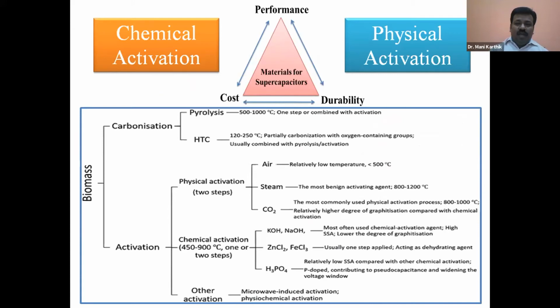Generally, for any biomass or carbon, pyrolysis, called carbonization, is the main step. You first need to turn the biomass into carbon, and that carbon should be very high purity, with no other impurities. For example, if any minerals are there, they will affect our performance. So 100% pure carbon can be activated by physical activation or chemical activation. In the physical activation method, you can use air, steam, or CO2 to activate your carbon at a certain temperature. This is well known in the literature.